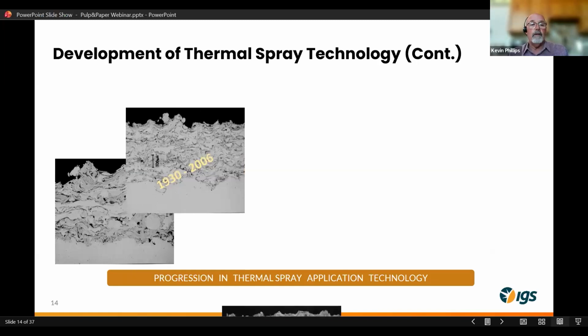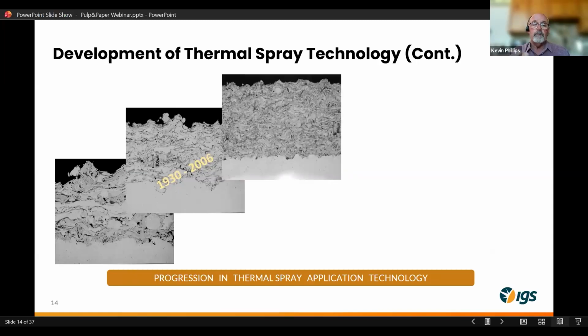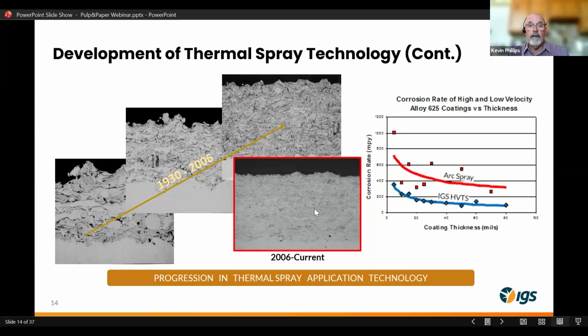These next few slides that I'm bringing up kind of give you a good indication of what I'm referring to as far as the oxides that are found in the older technology thermal spray that's available, in that when you look at some of these microstructures, you see these black indications within the cladding itself. Those are embedded oxides within the cladding. When you look at our IGS HVTS cladding, it is very dense. There's no evidence of in-flight oxidation in the final as applied cladding, thereby providing a better barrier, if you wish, to the sulfidation constituents that plague your equipment.